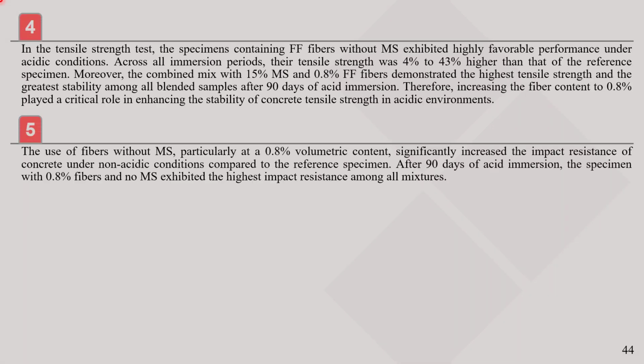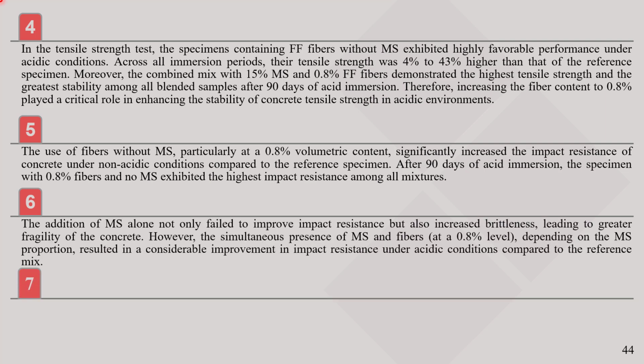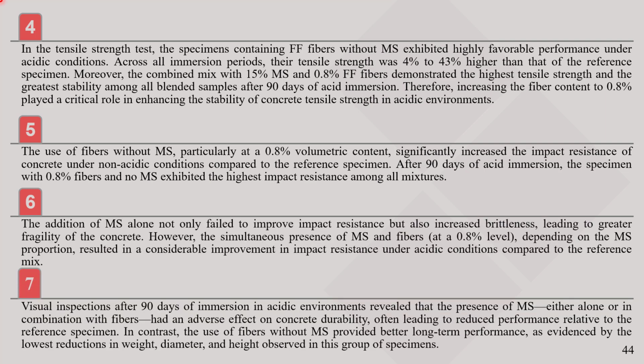For the indirect tensile strength test, similar results were observed. Fibers helped maintain the strength, while adding microsilica improved the concrete's microstructure, resulting in desirable tensile strength for the concrete samples. Regarding the impact test, it was found that fibers increased impact resistance, whereas microsilica caused brittleness and reduced resistance.